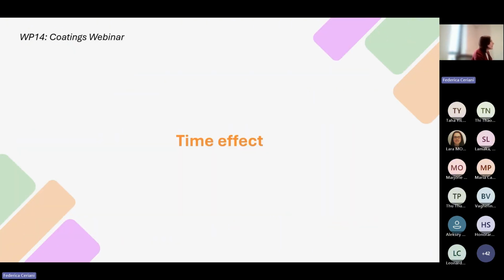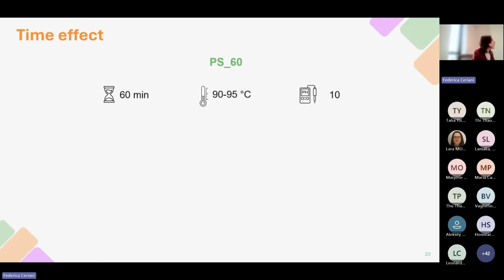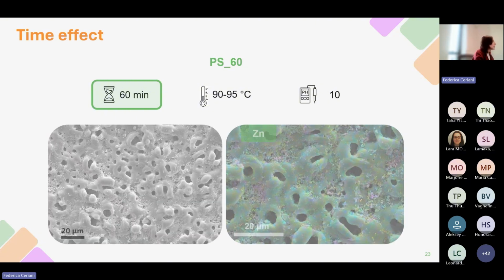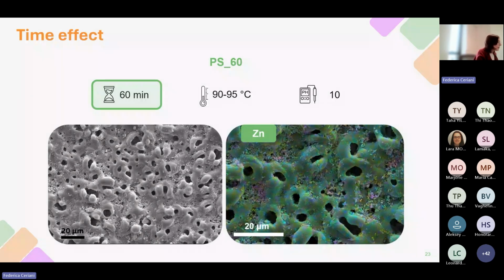Now we could introduce the second working variable that is considered, which is time. To evaluate the time effect, the duration of the sealing post-treatment is doubled and the PS60 sample is produced. By looking at the produced sample, we could note that even in this case, just few zinc-containing precipitates are present and pores are not clogged.